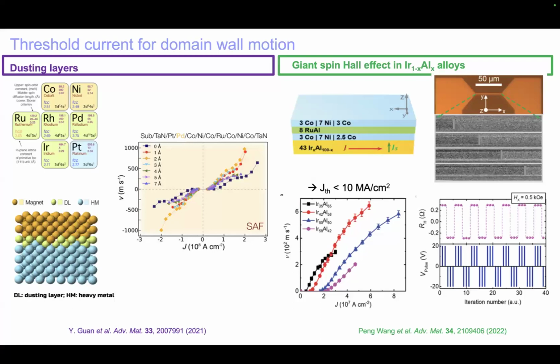Samsung, who supported some of this work, wanted to consider using racetrack to replace VNAND, the densest flash memory today. And they wanted the domain walls to move very slowly. That's a very slow technology. So they wanted us to demonstrate we can move the domain walls at very low current densities. And we demonstrated, indeed, we could reduce that threshold current density by more than a factor of 10 by changing the materials. And in particular, a very interesting material is shown on the right-hand side.